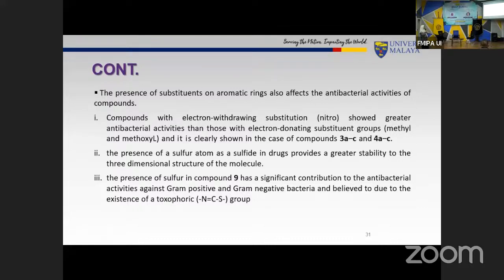And the presence of sulfur atom as a sulfide bridge, you saw sulfide bridge just now, provides a greater stability to the three-dimensional structure of the molecule. And finally, the presence of sulfur in compound 9 has significant contribution to the antibacterial activities, again, gram positive and gram negative. And it is believed to be due to the presence of N double bond CS group.